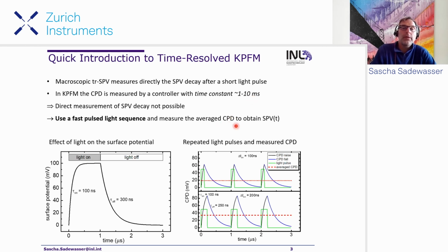So what you can do then is to apply these pulses, as was already introduced, and in difference to this pump-probe approach that Benjamin just introduced, we do it slightly differently. We still use the pulses, but we don't really have a probe pulse. So we keep on doing pulses in a regular way, and then we just measure the average of the CPD. Since our Kelvin controller is so slow, it will not be able to resolve each of these trajectories, but it will in the end give out an average value. Nevertheless, this average value still reflects to some extent what happens due to the exciting and the decay of the time-resolved sequence.